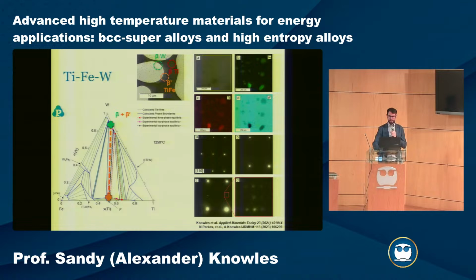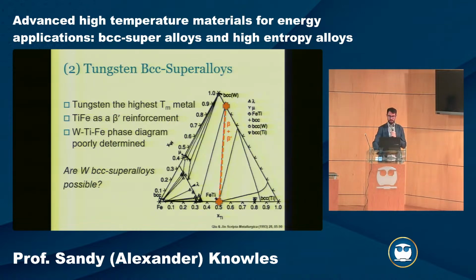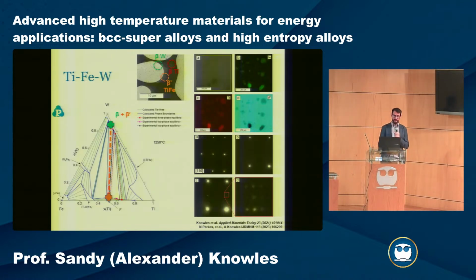The question we had is, going across this phase space, is there a two-phase line that goes all the way up to BCC tungsten? This would make the idea of a tungsten-based superalloy, which would be really cool if it was possible. So we make alloys, we choose different compositions, and we try to scan across the phase diagram, making steps in composition. This is an example of one of the alloys we studied, and I think it was 5 to 10 alloys with different compositions that we studied.